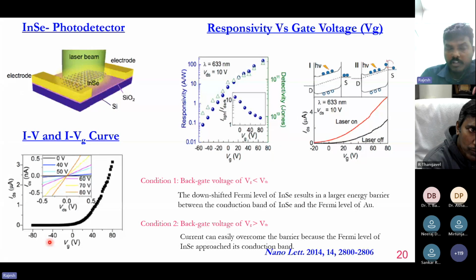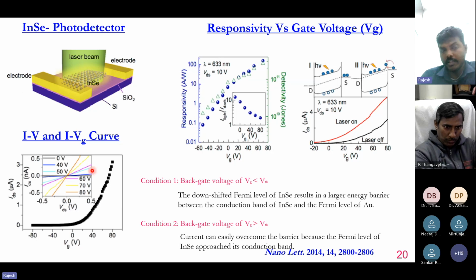So here we try to understand the nature of the material, whether it's N-type or P-type. For that, we apply the gate voltage from negative to positive. At positive gate voltage, we can clearly observe very high current. In case of negative gate voltage, there's less current, which indicates that this material is N-type. Because in N-type, when you apply positive voltage, the current will be high. In case of P-type, the current will be high in the negative region.